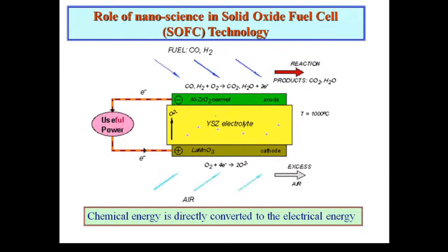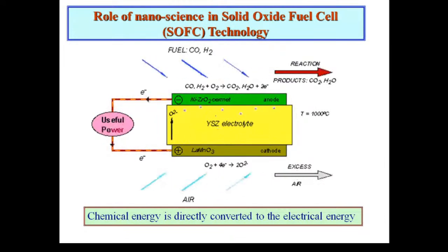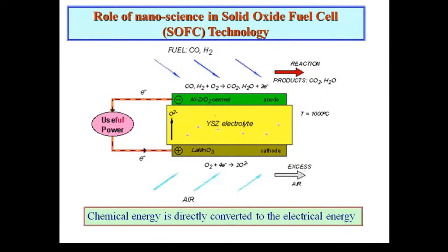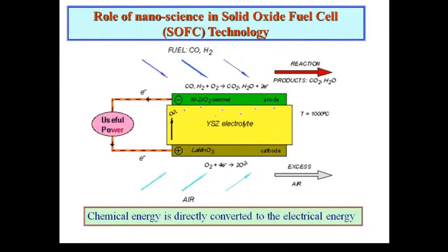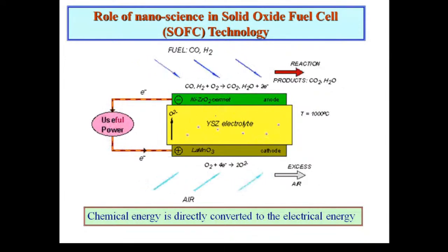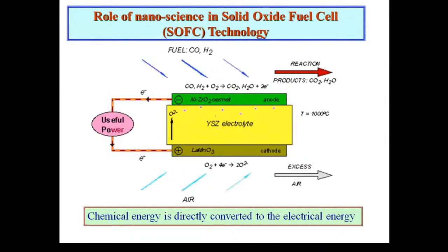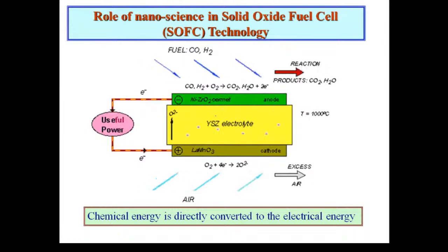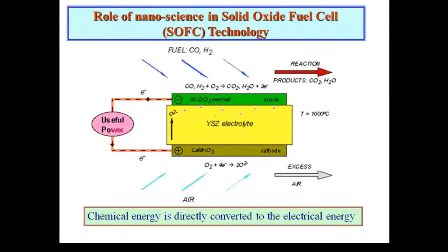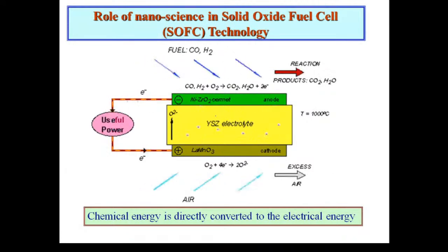In this, YSZ is named as the electrolyte. What is YSZ? YSZ is yttria stabilized zirconia. Basically, yttrium oxide is doped in zirconium oxide. Zirconium oxide is ZrO2, and if in ZrO2 we create some vacancy by doping yttrium, then it will form oxygen-deficient ZrO2, and the material will conduct oxide ions, but not at room temperature, at relatively higher temperature. What is the temperature? Around 1000 degrees centigrade. But 1000 degrees centigrade is not easily available, because making it is itself an energy-intensive process. But anyway, once the reaction starts, it itself generates heating, and that can be used to sustain this process.